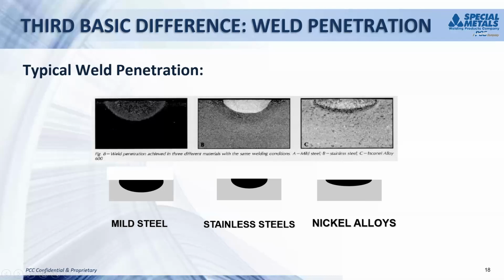And so if you look at the mild steel, the penetration is probably more than double the penetration in the nickel alloys. So you have to remember that when you're attempting to make repairs, or if you've got a tight rolled over bead in the edge of a base metal, you can't burn that out like you do with steel. You've got to take a grinder and open it up.